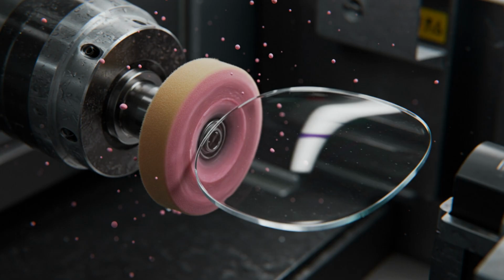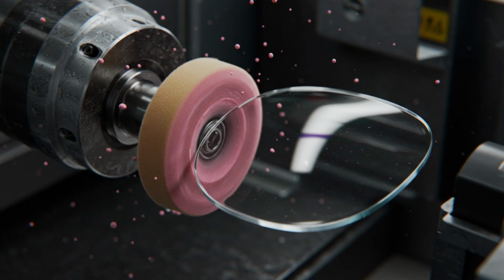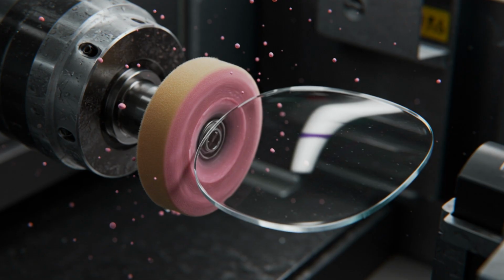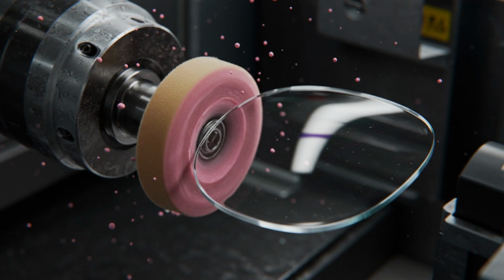This is where the magic happens. The lens is still translucent, but in the polishing stage, it finally becomes clear. Instead of metal tools, we use soft pads made of polyurethane or pitch, and a special polishing compound called cerium oxide. Cerium oxide doesn't just scratch the surface, it reacts chemically with the glass on a molecular level to level out the tiny peaks and valleys. This process is incredibly delicate.